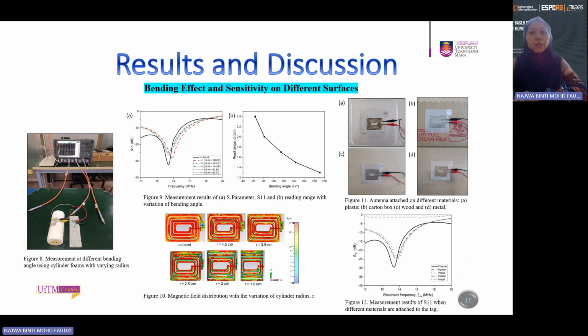So the effects of bending have also been observed and analyzed. The tag antenna was attached to different types of cylinder foam, and the shift of the antenna resonant frequency has been analyzed and observed using the VNA. We can see from the result here that the bending does not give a large impact to the tag antenna, where the resonant frequency is almost constant with the various bending angles.